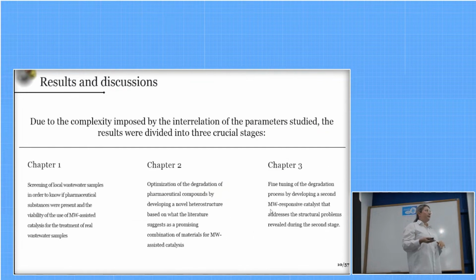So, due to the complexity imposed by the interrelation between the factors and the parameters studied in this thesis, we divided our results into three crucial stages. So for the first chapter, we present the screening of local wastewater samples in order to know if the pharmaceutical pollution is already present and the viability of using microwave-assisted catalysis for the treatment of real wastewater samples. Then in chapter 2, we present the optimization of the degradation of a few pharmaceutical compounds, where we develop a new heterostructure based on the suggestions of the literature as a promising combination for microwave-assisted catalysis. And then in chapter 3, we fine-tune the degradation process, where we develop a microwave-responsive catalyst that addresses the structural problems revealed during the second stage.